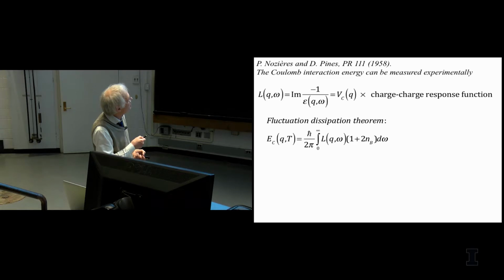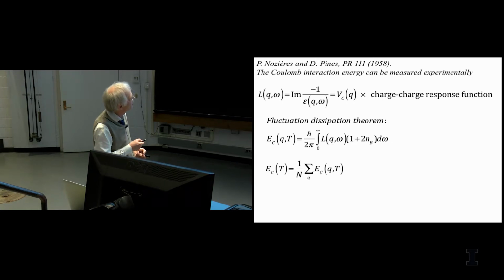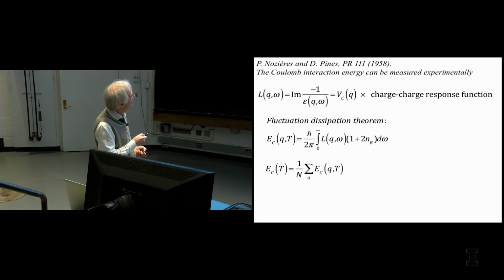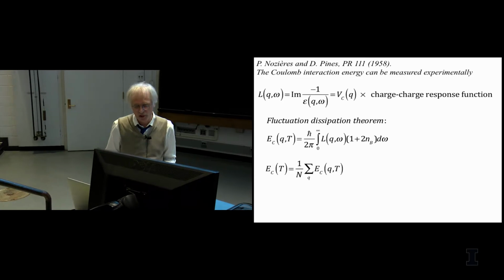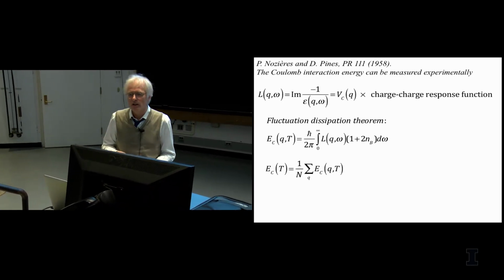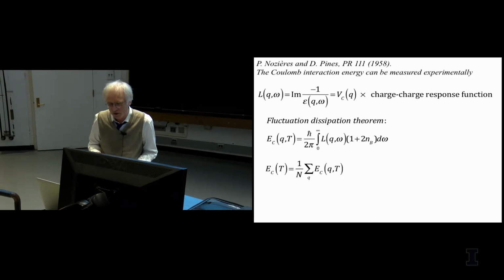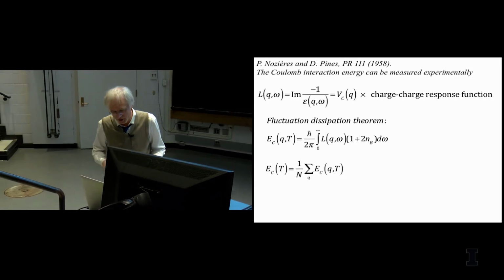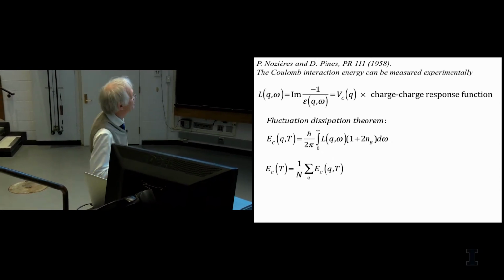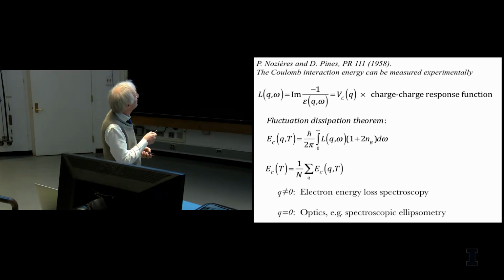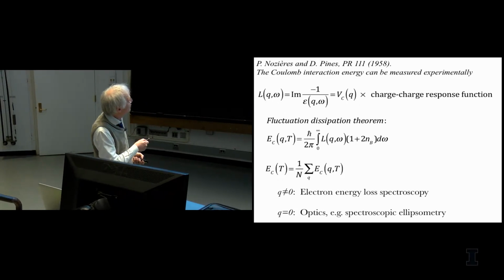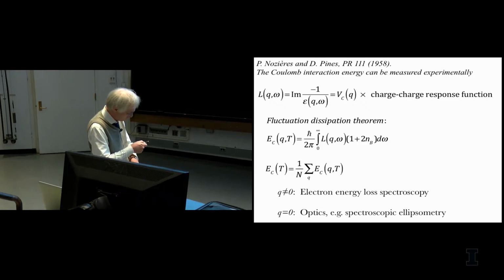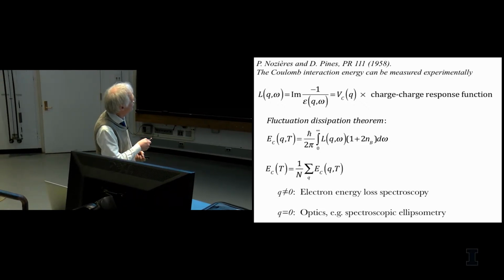And actually this fluctuation dissipation theorem relates this to the total Coulomb energy. It tells you that if you take this loss function, you integrate over all frequencies, multiply with a Bose factor correction, and you sum over all momentum, it gives you the total Coulomb interaction energy. This sounds like an oxymoron, but it's completely true. There's no way around it. It's not an oxymoron. It's a very subtle and nice result from the fluctuation dissipation theorem. So this can be measured at Q non-equals 0 using electron energy loss spectroscopy, that I will not talk about, but I will refer to it at the end. Or for Q equals or very close to 0 using optics, namely spectroscopic ellipsometry.